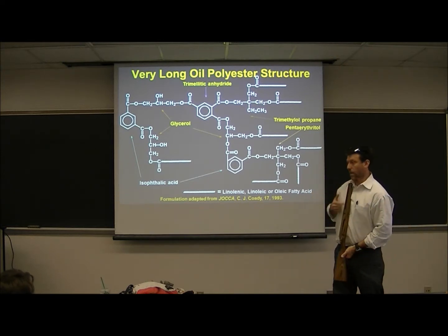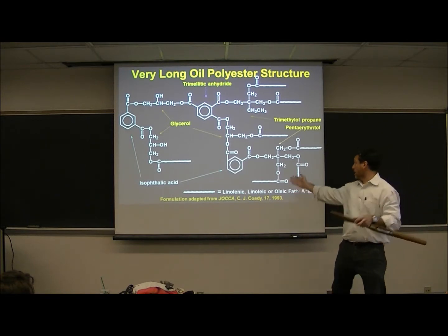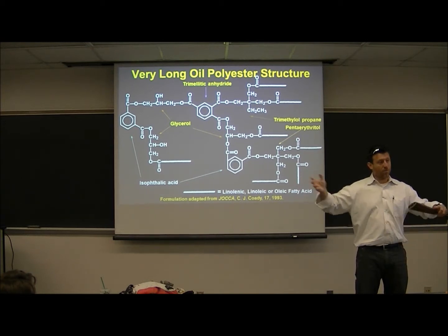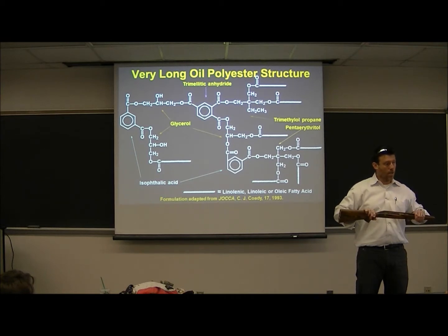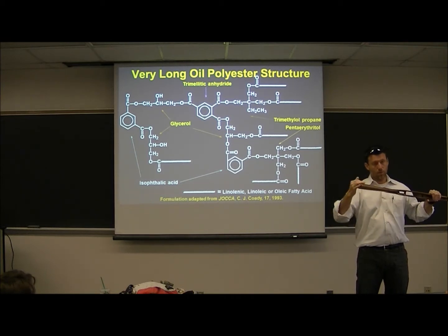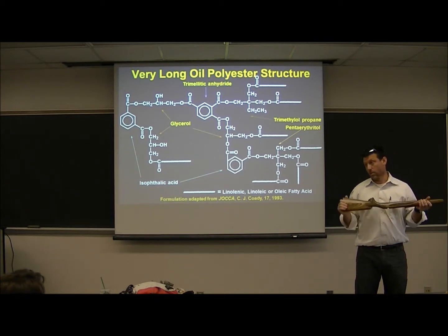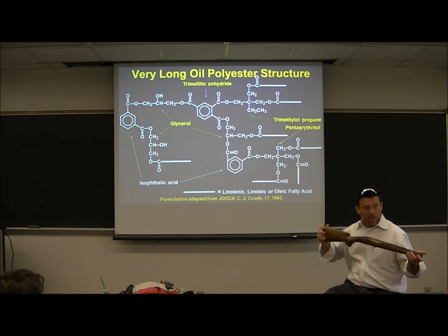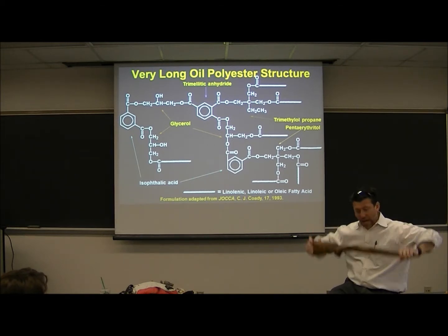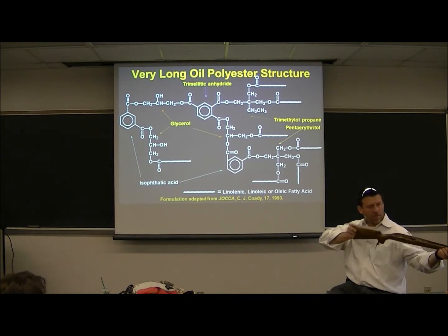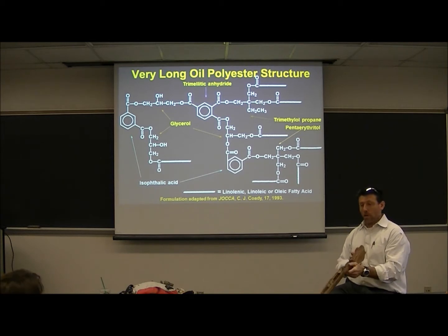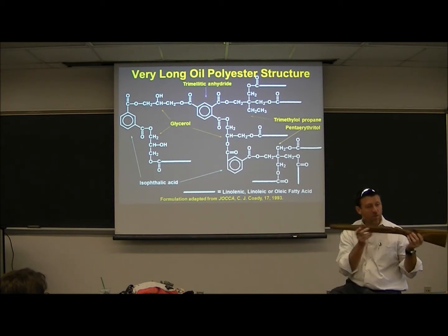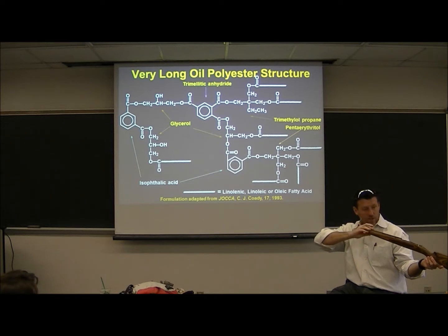And you can see where when we heated it, that resin kind of blows back out. But this resin is an alkyd, but an alkyd modified phenolic. Phenolic would be aromatic OH with some growth pattern. We'll get to that structure in 3 weeks. We'll be making phenolics. But the alkyd part loves the cellulose part of the wood. The phenolic loves the lignin part of the wood. Those are the two main compositional things. So this has, I think, 7 times the break strength in flex this way, and I think 5 times in flex this way, which is good. But most importantly, once that resin goes in and cures and seals, this doesn't have distortion when it's wet and dry. So you don't change the accuracy of the weapon.